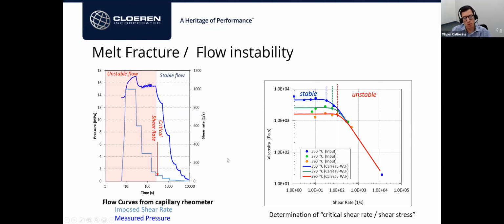And from there, we can convert that to shear stress and later viscosity. If you plot the resulting viscosity as a function of shear rate, we can clearly see a Newtonian behavior, and eventually those materials become very unstable. The flow becomes very unstable, and we have a very extreme shear thinning, which is actually a fake shear thinning. It's actually linked to slippage. We have some slippage going on.